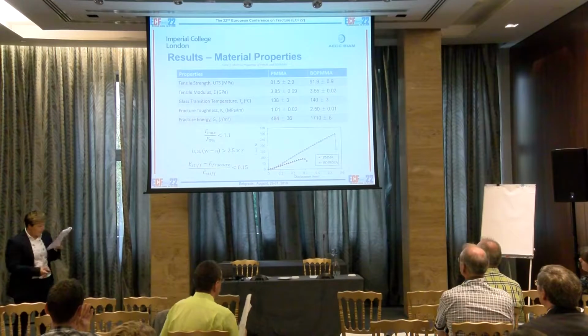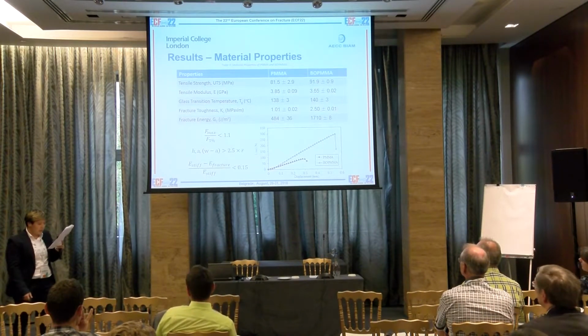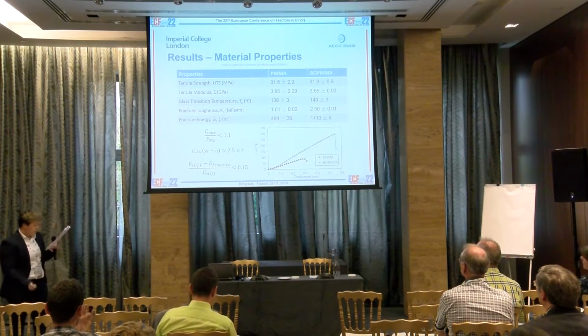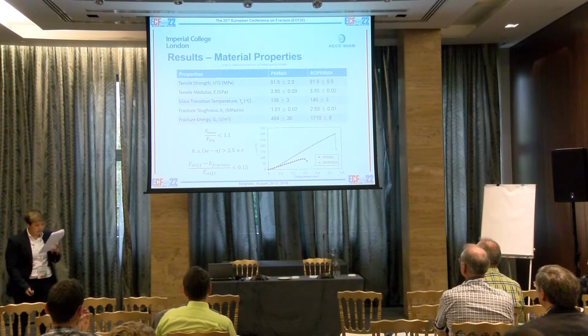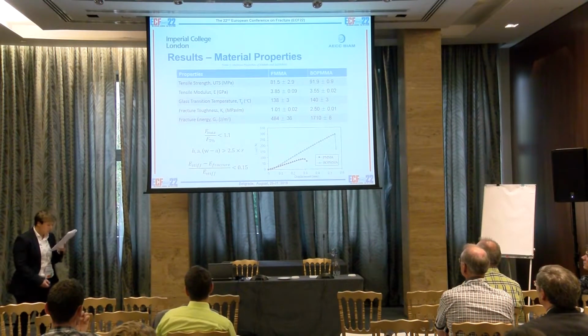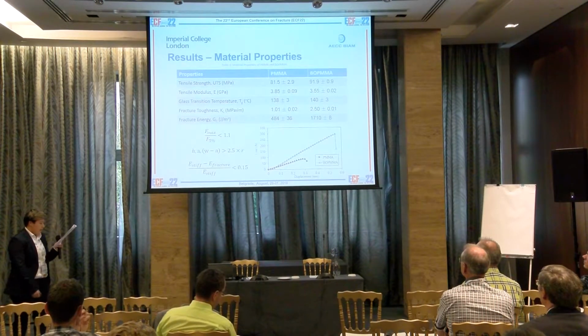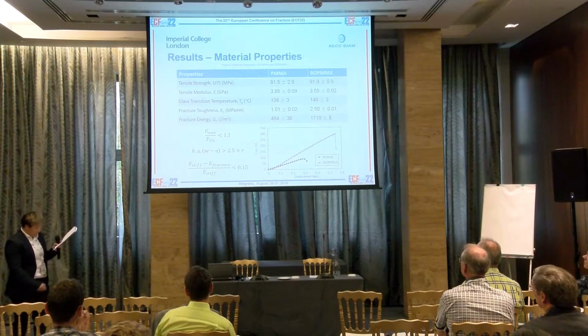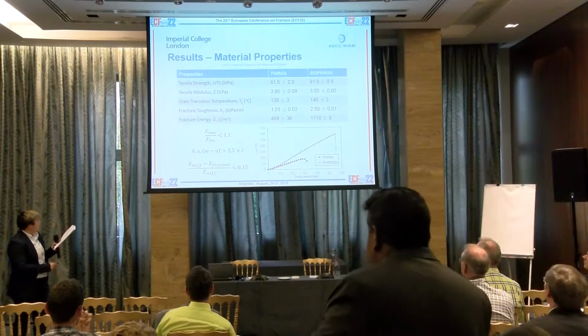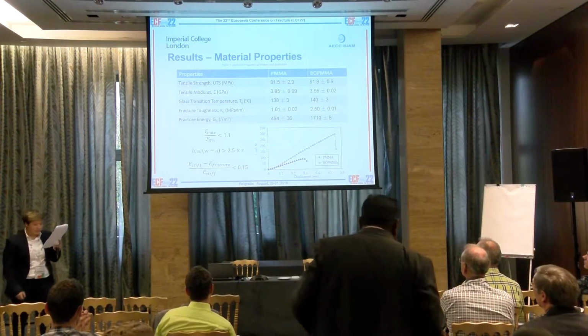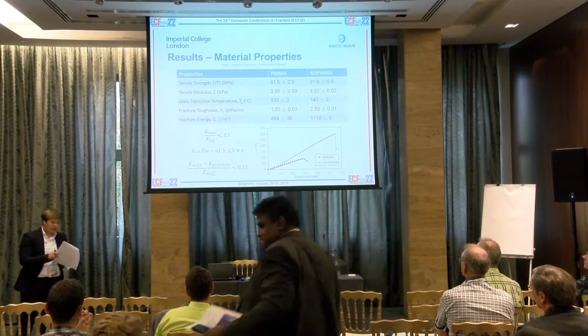The glass transition temperatures are similar in both materials, as the stretching process does not alter the chemical bonds within the material. The fracture properties of PMMA were enhanced with the 70% orientation degree, and this is reflected through the KC and GC values. Both polymers have passed the 3 LEFM validity checks stated in the ISO standard.